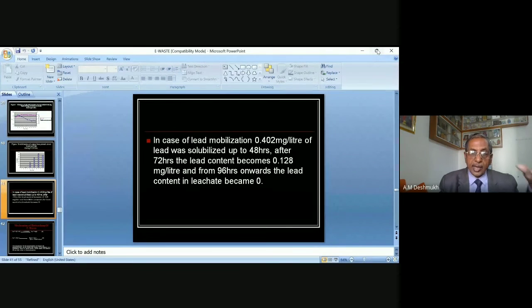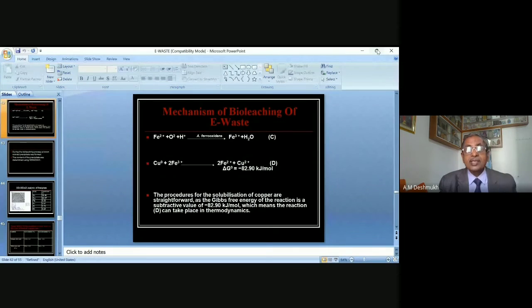Solubilization of copper from printed circuit board powder during 0 to 240 hours. We observed a peak at 192 hours. Means maximum copper was entering into the leachate. It was converted into soluble form from the insoluble form. So we were successful in isolating copper. We were successful in isolating lead also. Then what is the process? Very simple mechanism.